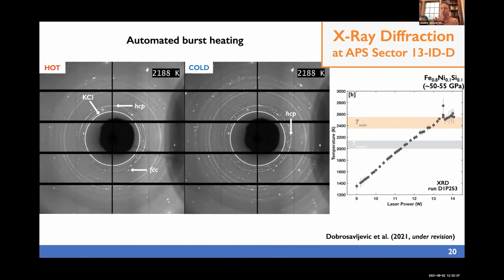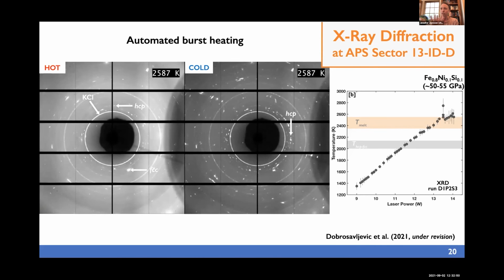What I'll show in the next slide is that using this technique allows for the detection of small amounts of melt, as opposed to having a very difficult time detecting a change in the background if one is not using the burst heating mode. There's a lot of scatter. And so what we use is pairs of these patterns. You also see recrystallization in these videos here.